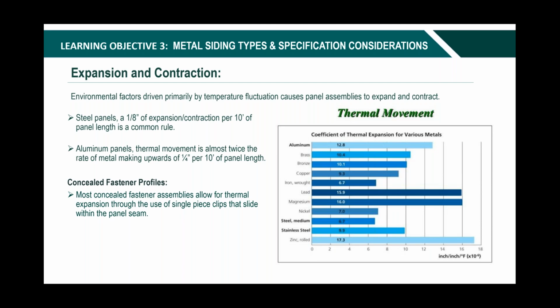So thermal movement, or expansion and contraction, is something that the environmental factors drive, primarily temperature fluctuation, causing that panel to expand and contract. Steel panels, 1/8 of an inch of expansion and contraction per 10-foot panel length is the golden rule. The aluminum panels, the thermal movement is almost twice the rate of steel, making it upwards to 1/4 inch per 10 feet of panel length. Most concealed fastener assemblies allow for thermal expansion through the use of single piece clips that slide